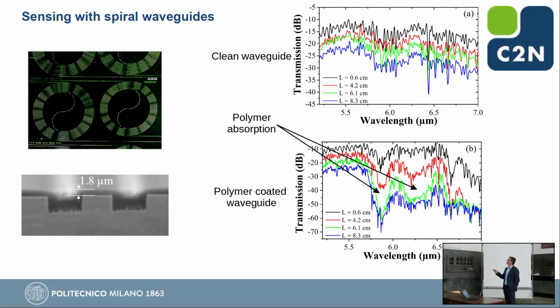So now if I make the transmission spectrum of the clean waveguide and of the polymer-coated waveguide, you see that we have some differences. And these differences actually correspond to the absorption induced by the presence of a polymer on top of a waveguide. And so, of course, the longer the waveguide, the more you see the effect. And so this is the first example of a sensing experiment.